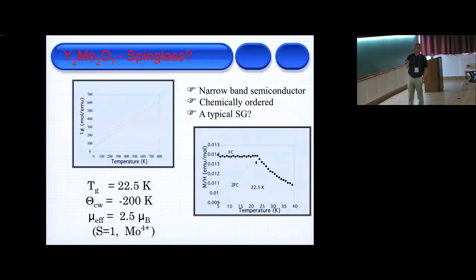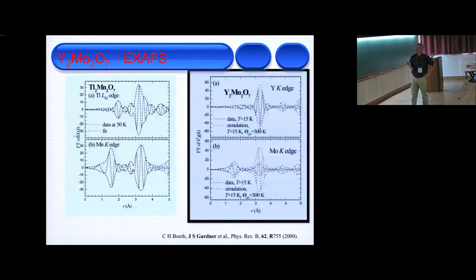Quickly, this is a glass, a spin glass, where there's no disorder. If you did that diffraction pattern, there seemed to be no disorder. But it's a beautiful spin glass with a very high transition temperature for something with no disorder. And you see here the Curie-Weiss temperature is very high, so the interactions are high.